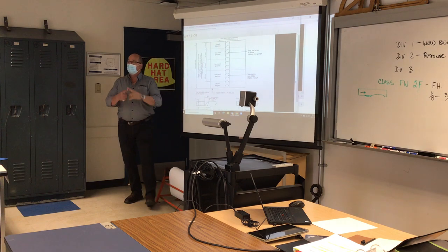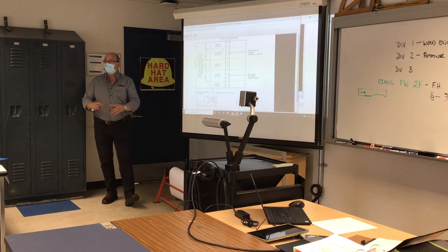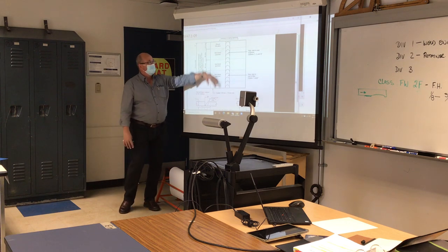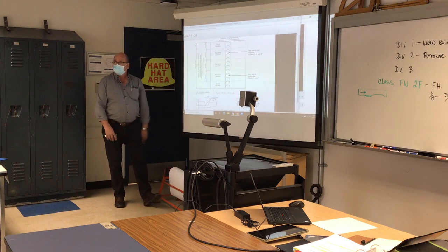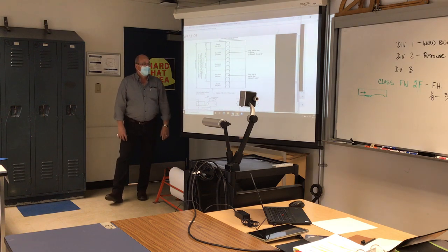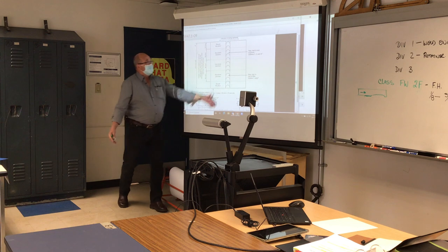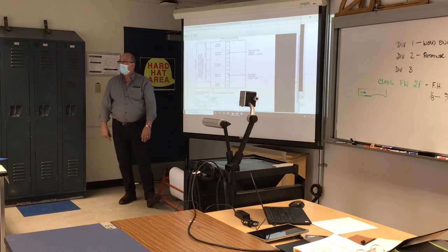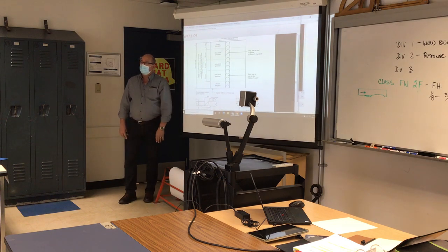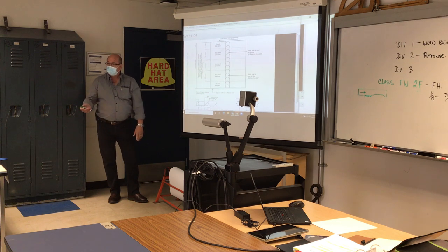When you've done that, I want the bottom of that weld completely covered. No gaps, no holes, no porosity, nothing. After that, I want you to weld that up nice and consistent, and then I want you to finish it with a nice cap that's no more than 10% reinforced over the width of the weld. We're then going to grind this down nice and flush. You're going to show me how well you can grind. We're going to take the backing bar off the back, and we're going to grind that down. Either we're going to plasma it off, or we're going to gouge it off if we want to validate gouging.